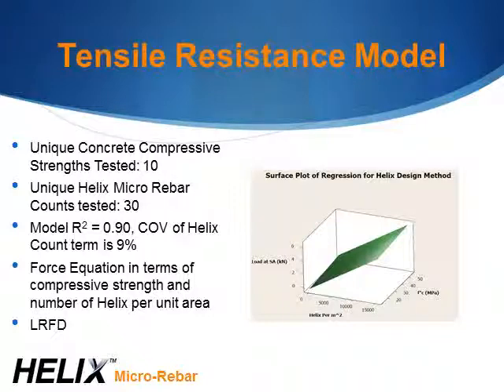So we ran 10 different compressive strength mixes with 30 different Helix quantities and developed a multiple regression model that had a high level of significance, a high R squared of 0.9, with a relatively low coefficient of variation in the term, only 9%. So with relatively high statistical significance, we're able to predict the amount of force that a given number of Helix provides in tension.